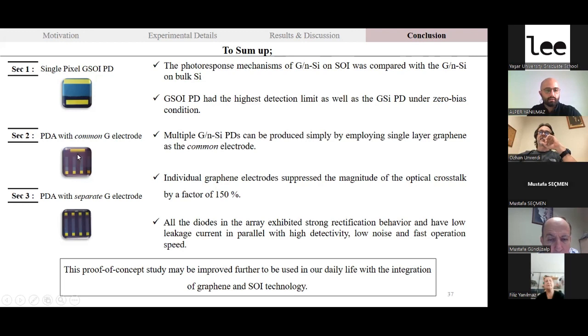In the second section, we fabricated the photodiode array with a common graphene electrode, and then the second device structure, the individual one. We observed that multiple photodetector arrays can be produced simply by employing the single layer graphene as a common electrode, and the individual graphene electrodes suppressed the magnitude of the optical crosstalk by a factor of 150%, and all diodes in the array exhibited strong rectification behavior with a fast operation speed. This is a proof of concept study, and it could be improved further to be used in our daily life with integration of graphene and silicon-on-insulator technology.